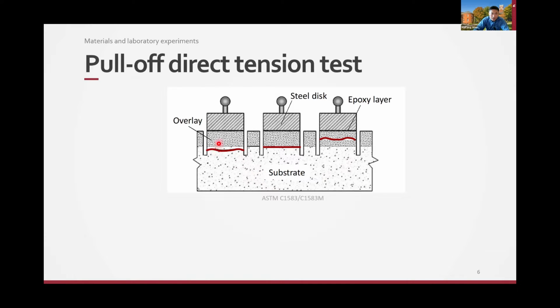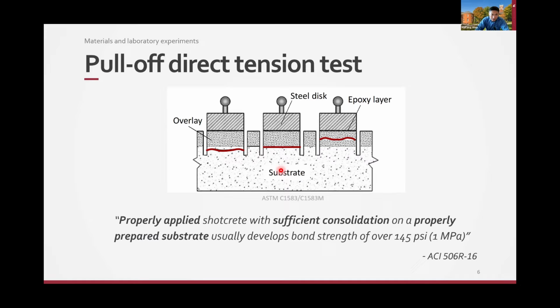You apply the shotcrete, and then you drill into the substrate and use epoxy to attach a steel disc, and then you pull until there's a failure. So the failure can be within the substrate, at the interface, or within the shotcrete, depending on the conditions of the shotcrete, the bond, and the substrate, whichever is stronger or weaker. So it can happen in all those three scenarios.